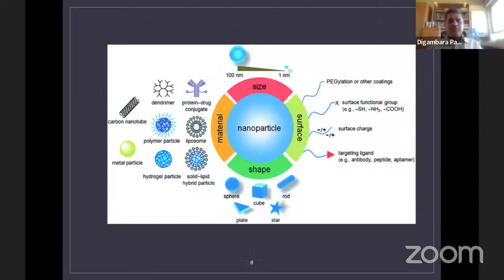When we prepare metallic nanoparticles, the main challenge is how to stabilize them. Nanochemistry was not developing because when we were preparing metal particles, the particles were not getting stabilized in the nanometer region. One way of doing this is to modify the surface of the nanoparticles with different organic or inorganic ligands, and this is where we can manipulate the size. Based on the synthetic procedure, there are many ways: you can do physical methods, chemical methods, or biological methods.